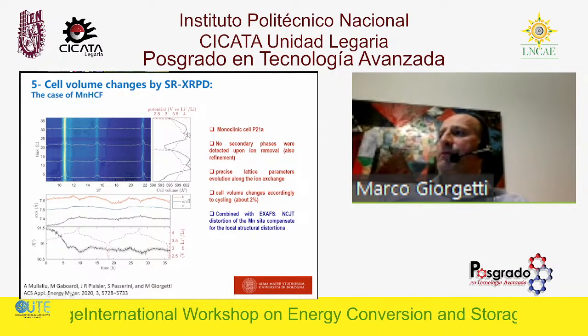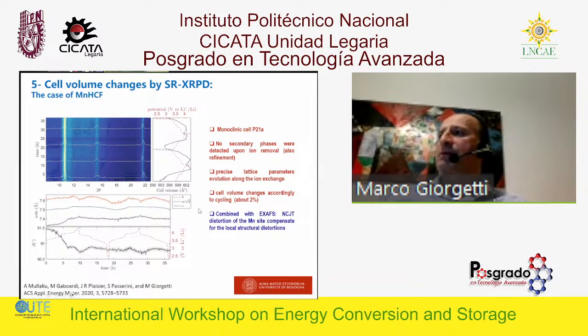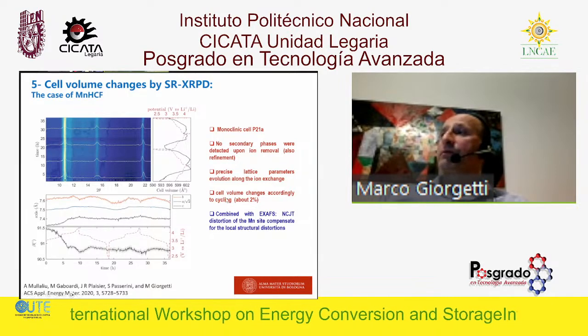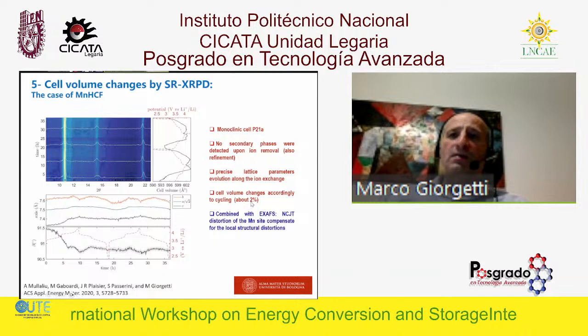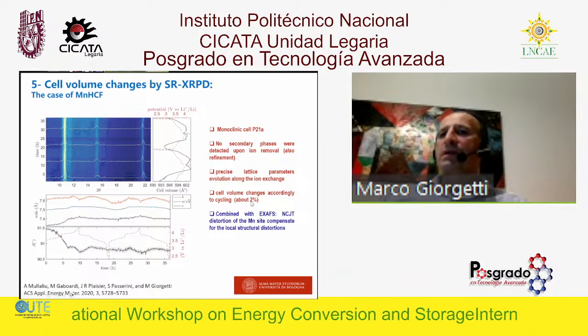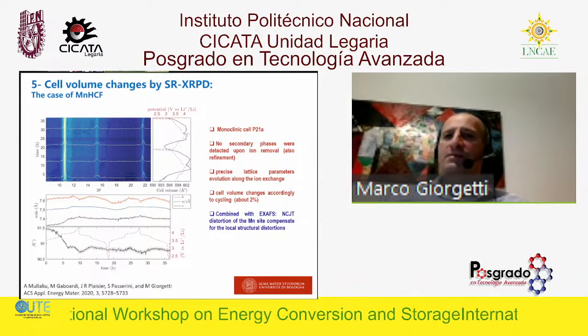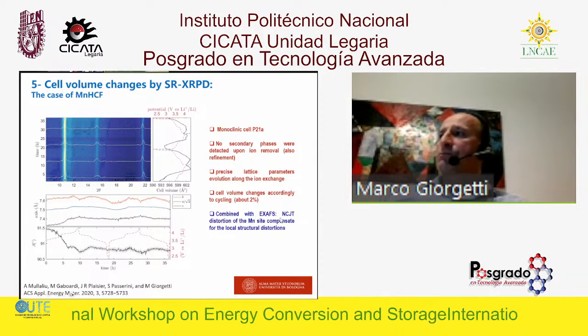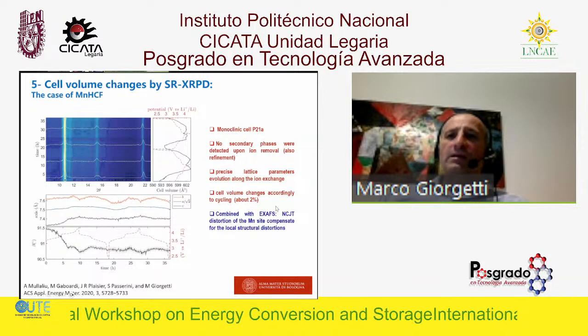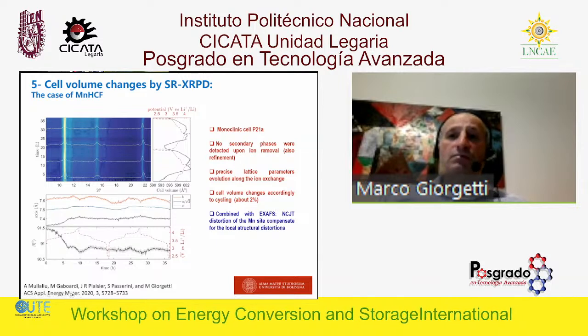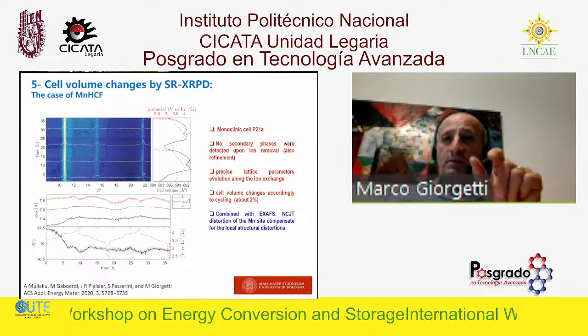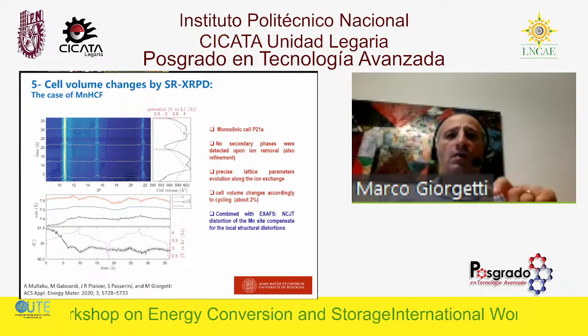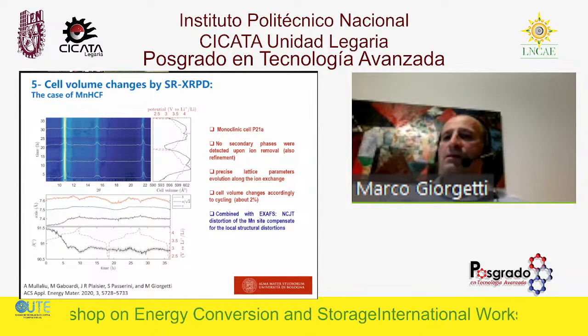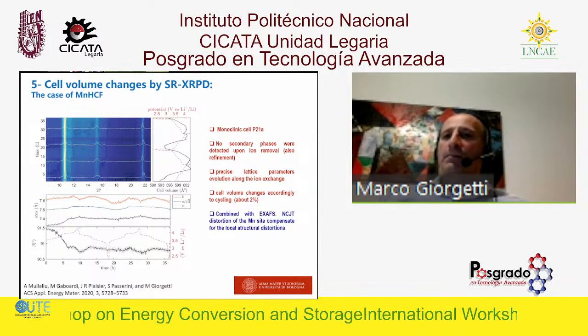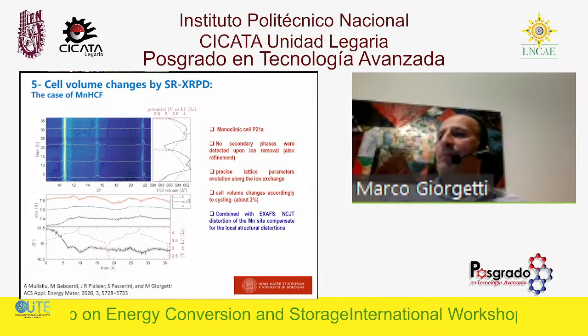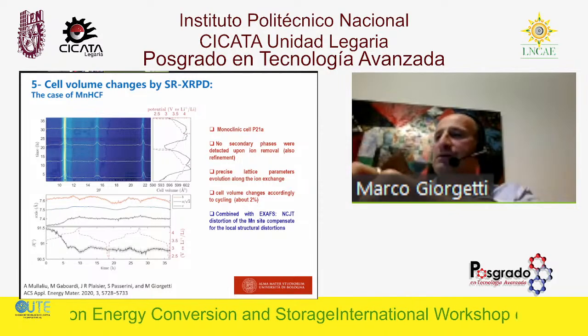Precise lattice parameter evolution on ion exchange is indicated here. But what is important is the cell volume changes only about 2%. So that was very interesting. So we concluded that a non-cooperative Jahn-Teller effect is taking place. And this strong local structure distortion is mitigated by the periodic extended structure. And that's why the capacity fading maybe is not that dramatic in the case of the sodium batteries.